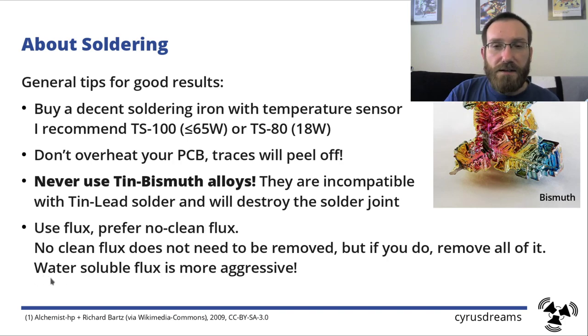And you can get water soluble flux and water washable flux. You might think it's the same as with paint, where the water based stuff is better and less toxic. In this case, it's the complete opposite. The water soluble flux is more aggressive stuff than the no clean flux. And it's water soluble because you have to remove it. If you don't remove that one, within weeks it will eat away your PCB. So don't go for that stuff.